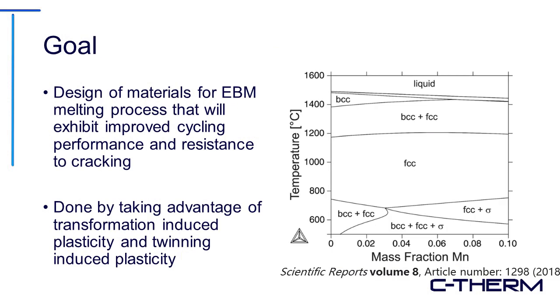So the goal of this paper was to design new materials for this melting process that would exhibit improved cycling performance and improve crack resistance. And what they wanted to do was construct a phase diagram so that they could take advantage of transformation-induced plasticity in the alloy, and also some twinning-induced plasticity to reduce the likelihood that the part would crack.